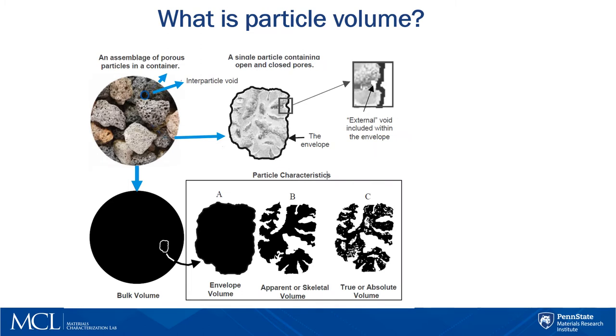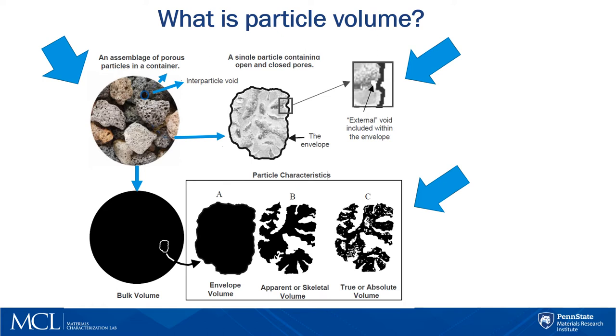Here you can see an illustration of various volume types. At the top left, there is a container of individual particles illustrating the characteristic of bulk volume, in which inter-particle and external voids are included. At the top right is a single porous particle from the bulk, with the particle cross-section shown surrounded by the envelope. In the illustrations at the bottom, black areas are analogous to volume. Illustration A is the volume within the envelope. Apparent or skeletal volume B is the same volume minus the external volume and volume of open pores. And C is the volume within the envelope minus both open and closed pores.